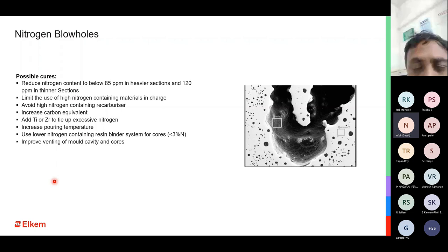Possible cure, very similar to the other case. We have to reduce nitrogen content to less than 85 ppm, and maybe about 120 ppm in thin sections. How do we do that? We have to ensure that nitrogen-containing materials in the charge or in the recarburizers are controlled, so that we do not have a sufficient amount of nitrogen coming into the system. Adding titanium or zirconium can be a solution. Titanium is a strict no-no in ductile iron because it's an anti-nodularizer, and more titanium means nodularity comes down. So a zirconium-based inoculant, or even ferrozirconium, can be a way out to control nitrogen fissure or nitrogen blowhole defects inside the casting.